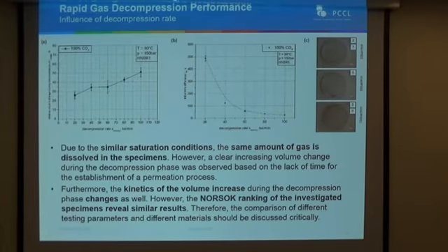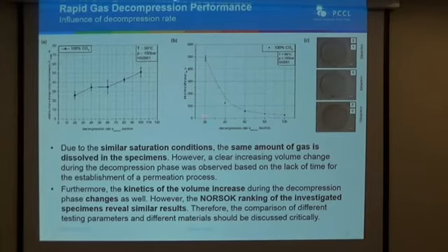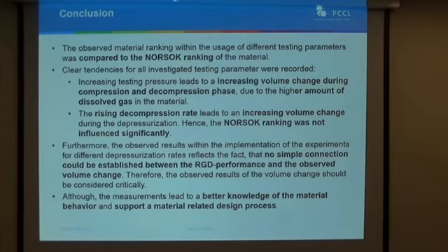And this brings up the question whether the NORSOK ranking is sensitive enough for material characterization in this field, and also to assist a future material development process. The knowledge of a volume increase during pressurization and during depressurization is very important.